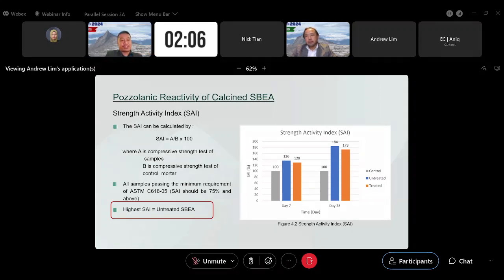But to answer your question, yes. From my other test, which is not covered in this presentation, there is an optimum level of replacement. If not mistaken, because I did not go through my notes before this presentation, I think it's about 20 to 30%. That's where you get the maximum strength, which is why I call it the optimum level. If you put in more than 20 to 30%, you get a reduction in strength. Anything less, you also get a reduction in strength. You don't achieve this high strength.